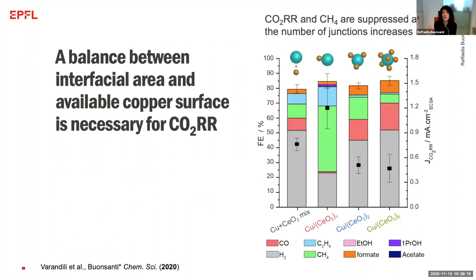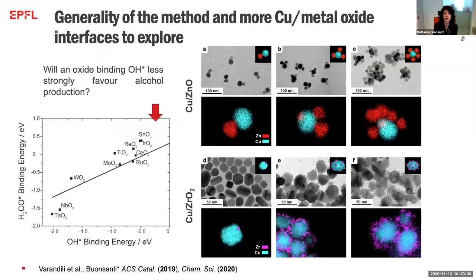Now, what we found here was a bit contrary to our expectations, because what we found is actually that as the interface between the copper and the ceria increases, so as we add more spheres of ceria, the CO2 reduction is actually not promoted at all. So what we learn from here is that, okay, the interface is important, but because it eventually is the copper that is active towards the CO2 reduction reaction, we do need to have a good balance between the interface area and the surface of copper that is available for the reaction to occur. We are still looking a bit more into the details because actually here the story is a bit more complicated than how I'm presenting, but I will say that this is the main conclusion that we get so far.